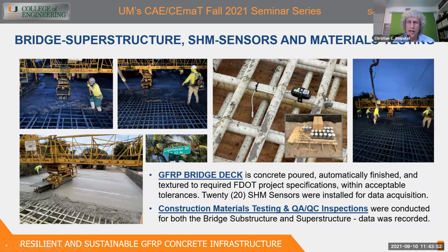And essentially, these allow us to record data for a minimum of 60 days. Mine actually lasted about 64 to 67 days. For DOT, if you don't know, we typically run 2, 7, 14, 28-day concrete breaks. And if the 28-day break does not come up to the minimum required, in this case 5,500 PSI, we usually run a 56-day break.